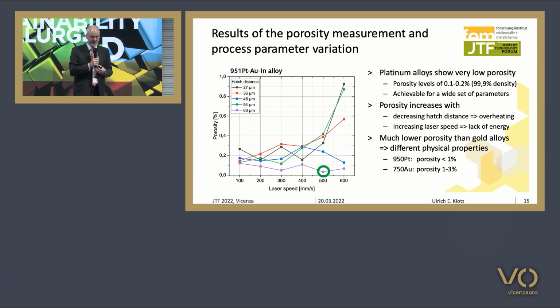We see that the hatch distance has actually a quite strong effect on the porosity, especially at higher laser speeds. With decreasing hatch distance, the porosity increases, and this is probably due to overheating, because more material is melted several times.